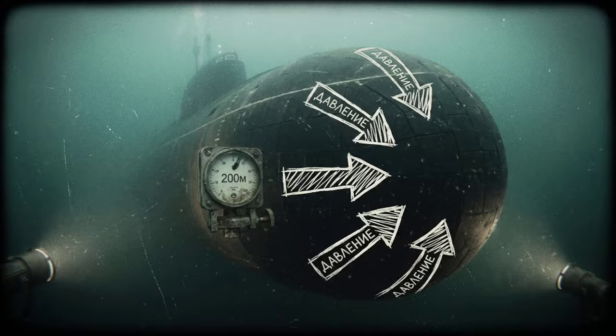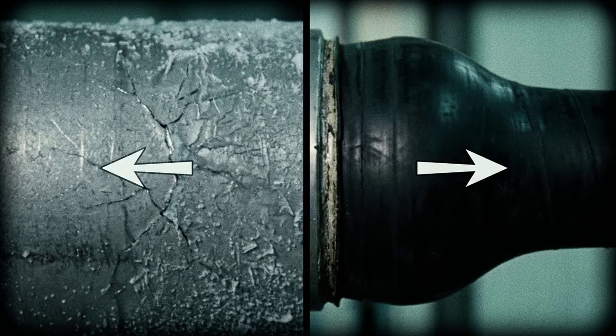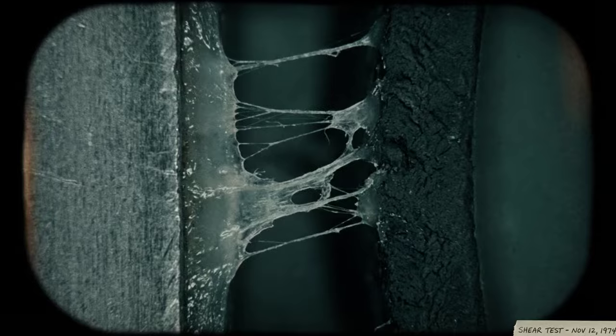That pressure compresses the rubber matrix unevenly because the inner bonding layer is shielded by the tile itself and experiences lower stress. Meanwhile, the steel hull underneath cools as the submarine descends from 18-degree surface water into 4-degree deep water. Steel contracts as it cools. The outer rubber tile surface, compressed by seawater pressure, actually expands slightly. This creates a differential. The steel shrinks while the rubber grows. The mismatch generates shear stress at the adhesive interface, trying to peel the tile away from the hull.